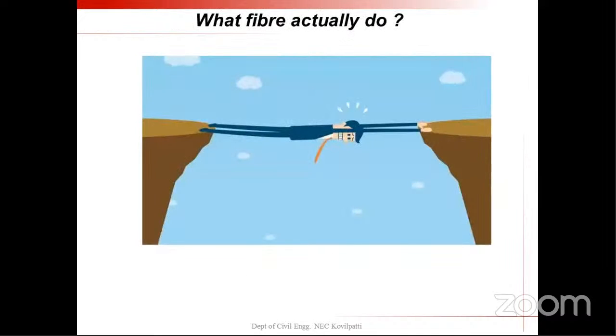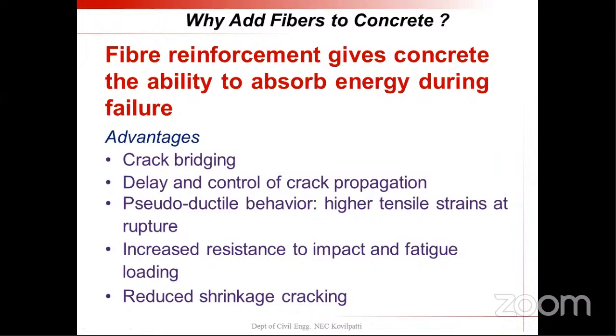So this is what fiber actually does. It is not going to improve strength by itself. It is just going to bridge across the cracks, improve the stress transfer and increase the tensile strength. So the main mechanism for adding the fiber is crack bridging. It is not only bridging the crack, sometimes it is delaying the formation of the crack. It will take large amounts of tensile strain before rupture, and especially it provides more resistance during impact and fatigue loading. And microfibers, which are smaller in size, are particularly used in places where we want to reduce shrinkage cracking.